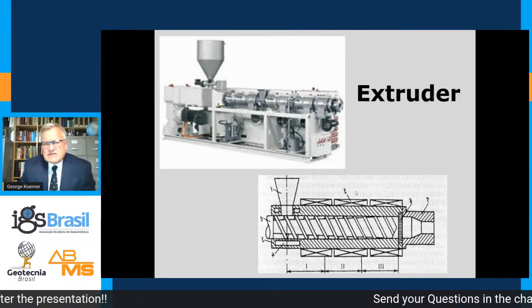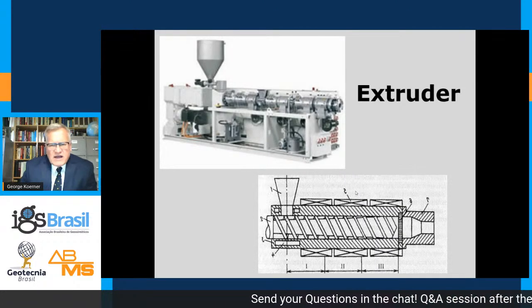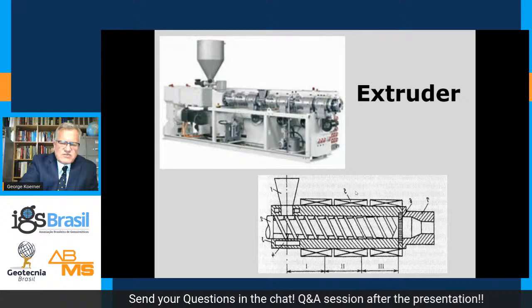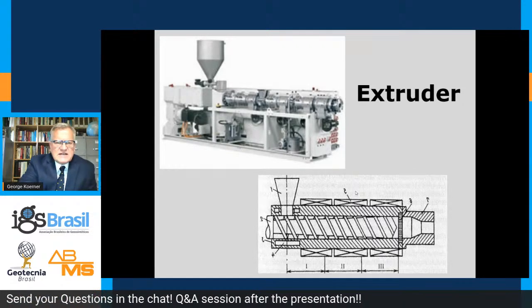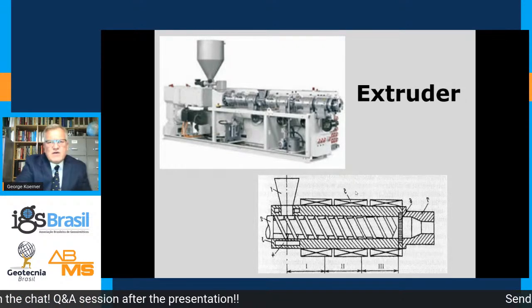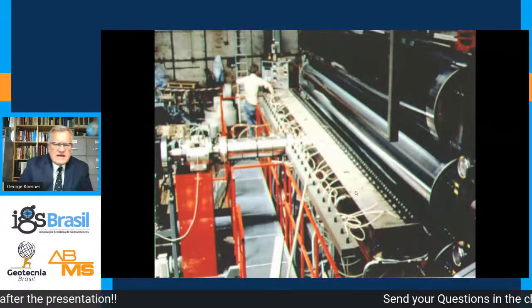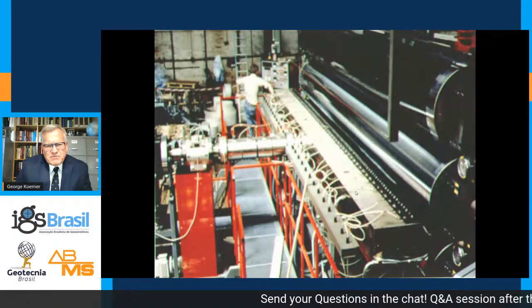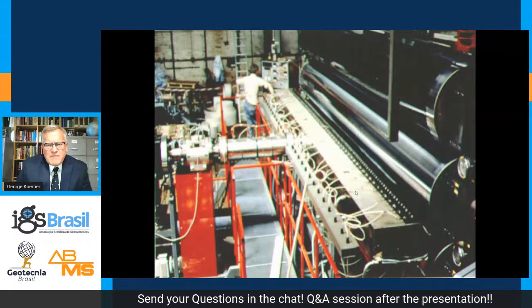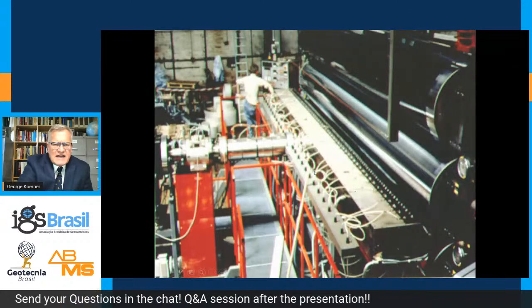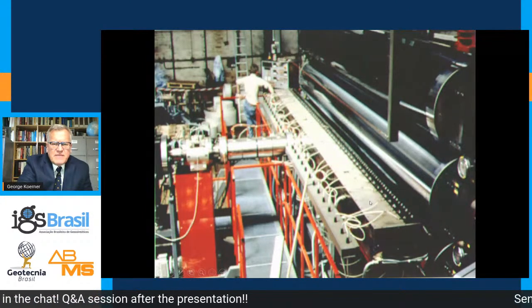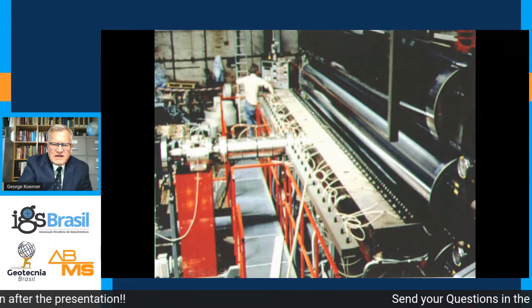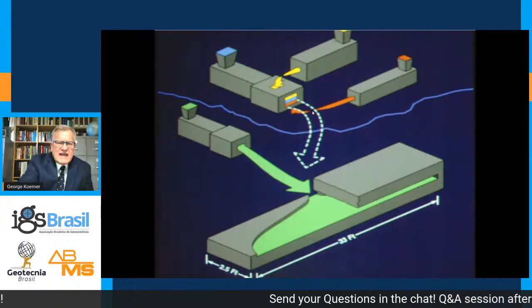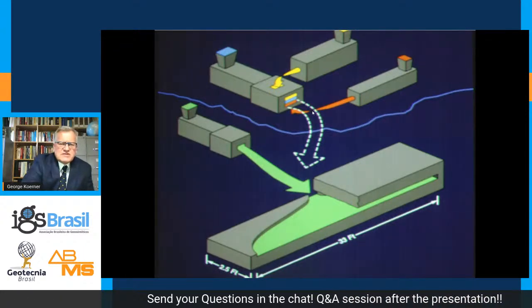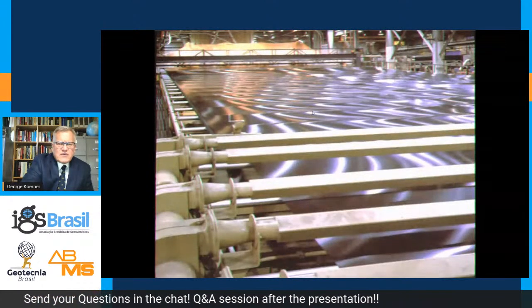Now we'd like to introduce that letdown and regrind into the extruder. That extruder is basically a large Archimedes screw with heaters on the side of it. It then feeds a die. In this particular case, it's feeding a wide mouth die. This die lip is about 10 meters across, so it's a very large die. It can be fed by multiple extruders and is spread out quite wide.